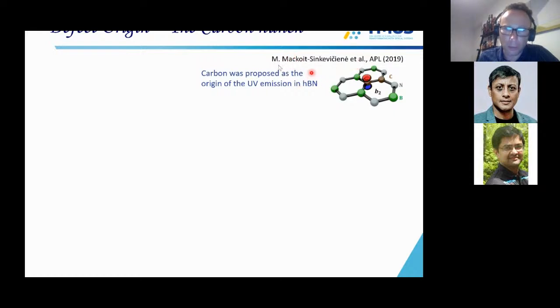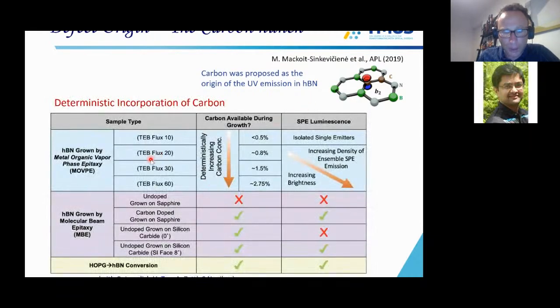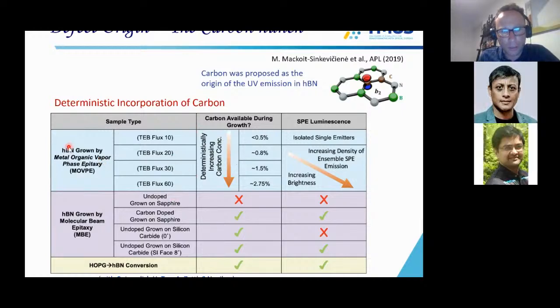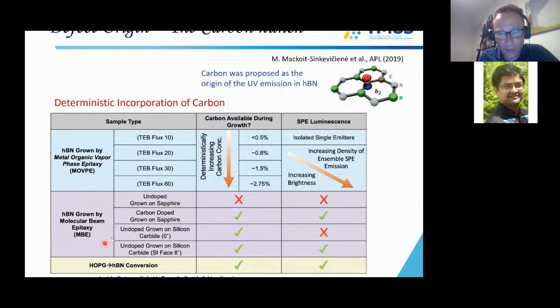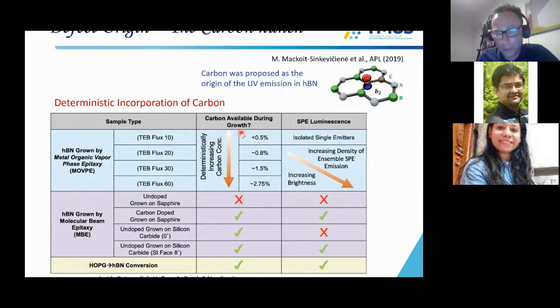This is by the group of M. Mackoit-Sinkevičienė that proposed that carbon is the responsible emitter in the UV range, and so what we did is, and you can ignore the details, I will just guide you through this table. We decided to partner with people that can grow wafer scale hBN by using MOVPE, a metal organic vapor phase epitaxy method, and MBE and other methods. And we saw increased luminescence intensity with an increased carbon doping. Basically everywhere where there was carbon, there were emitters, and where there was no carbon, there were no emitters.